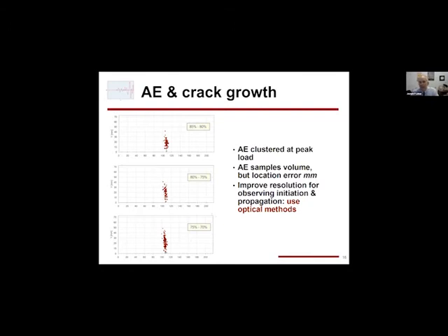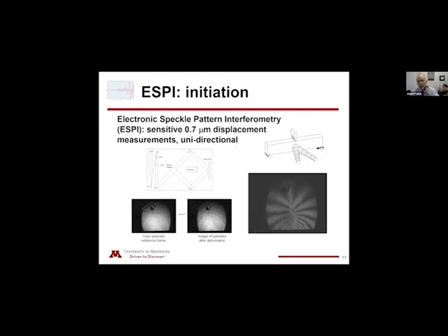So we've done that. We started with speckle interferometry, and certainly this is a technique that other people have used. So we copied from work at Northwestern with Professor Shah's group. The nice feature of speckle interferometry is that it's simply based on optics. So the processing of data is trivial. Setting up the optics is quite challenging. So what I'm showing here is a condition that is measured at peak load. And these fringes that develop are due to what I would describe as a displacement discontinuity, a fracture that's forming at the bottom fiber of the beam.